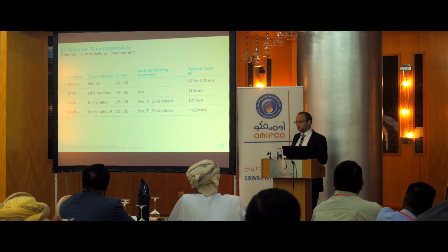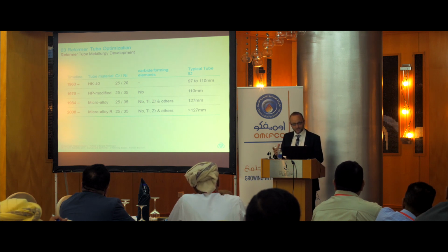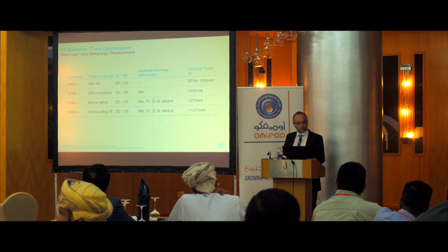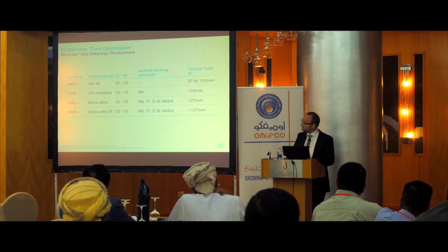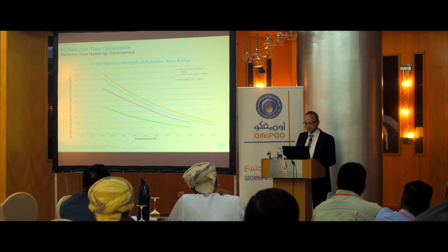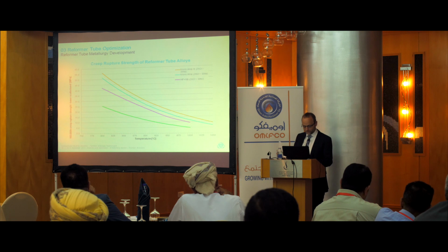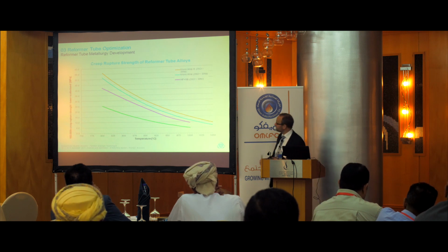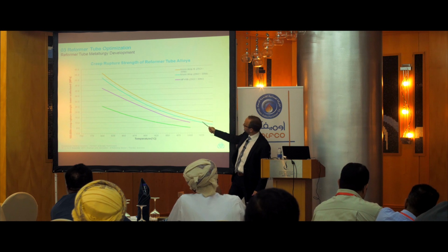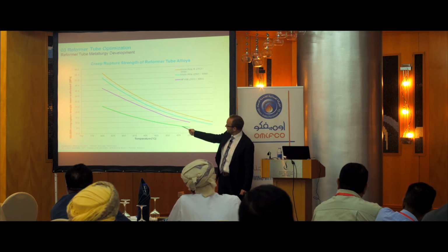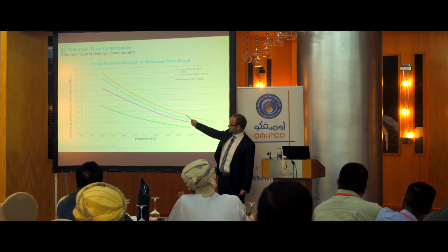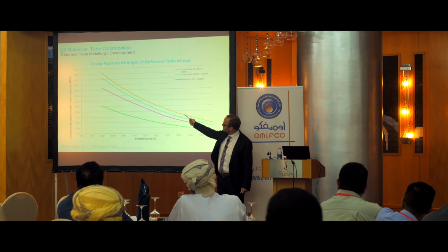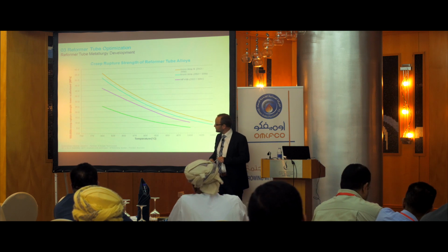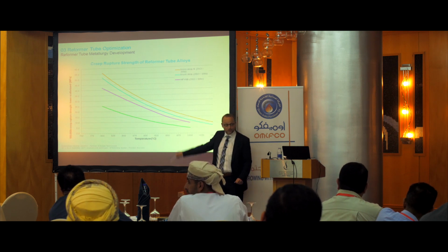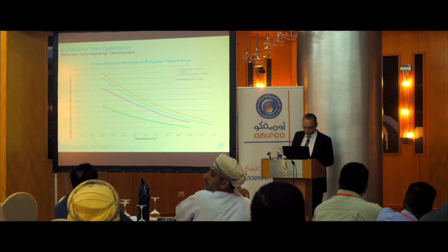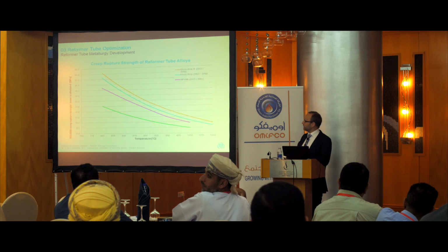Secondly, the fabrication process, so the melting and casting process, has been optimized and is much more precise, and this results in a higher strength of the tube material. So this is the effect of the development over the years. That's HK40, HB modified, and these are the two microalloy parts, where the microalloy R, the latest one, has about 15 to 20% more creep rupture strength than the old microalloy.